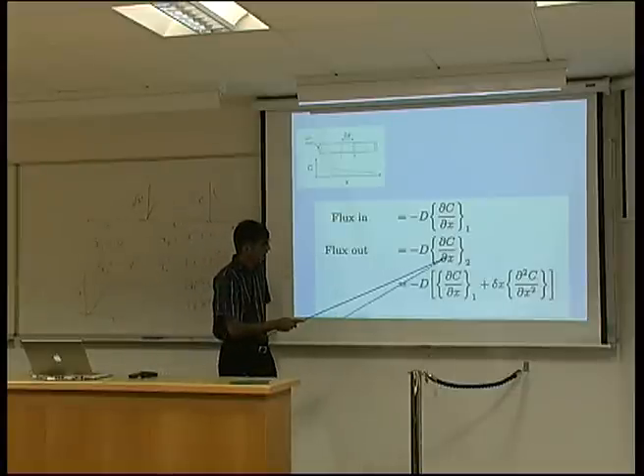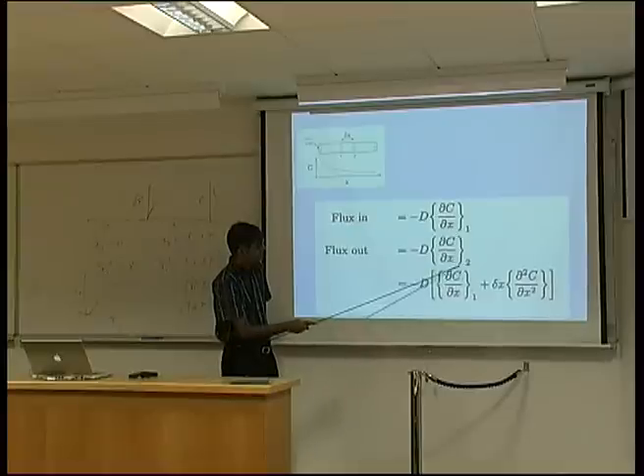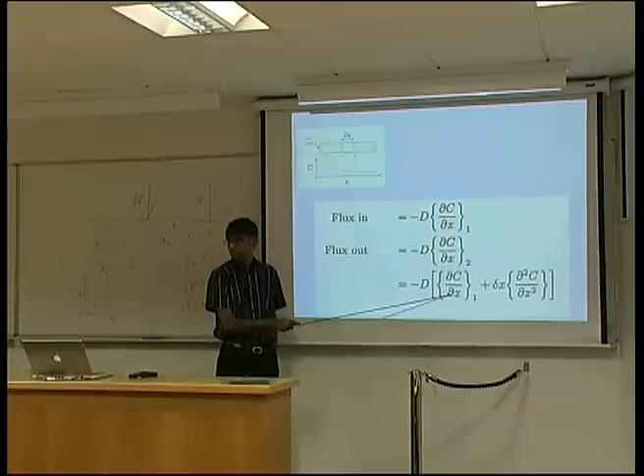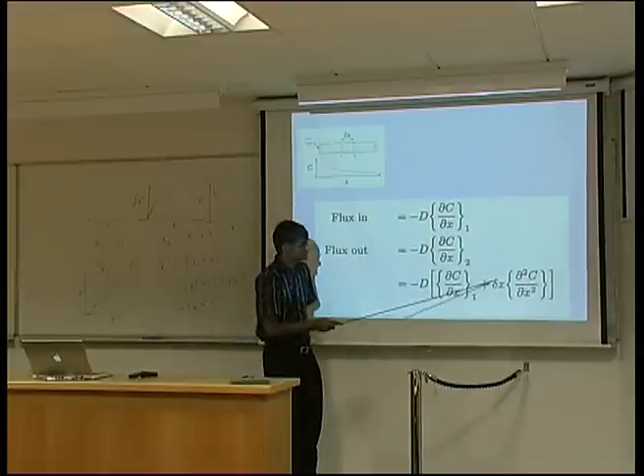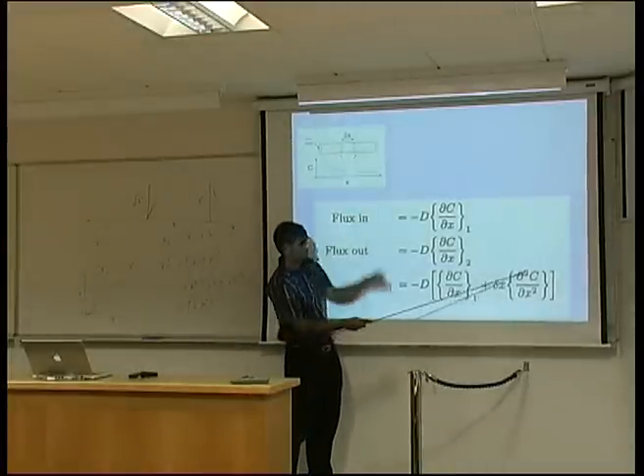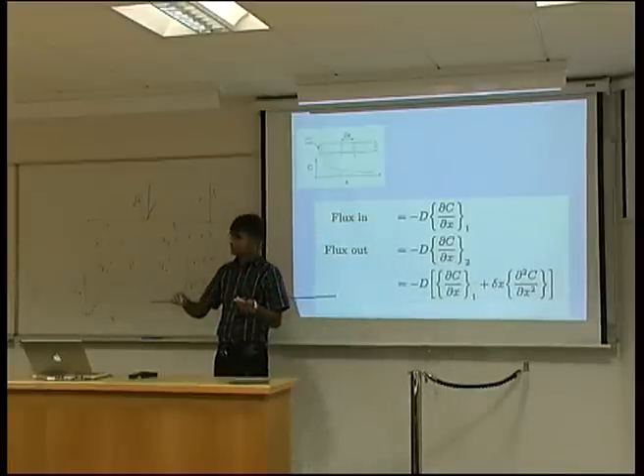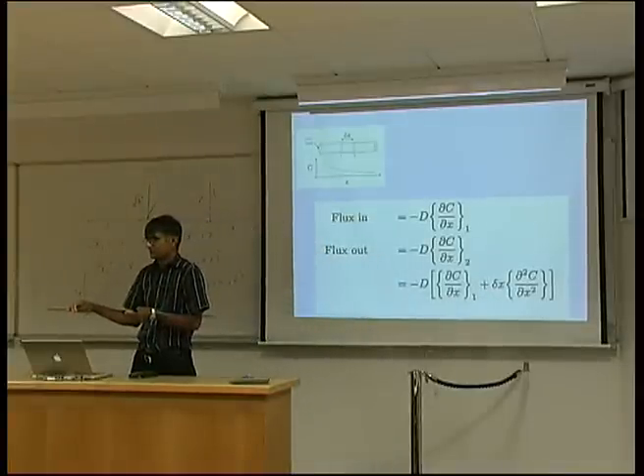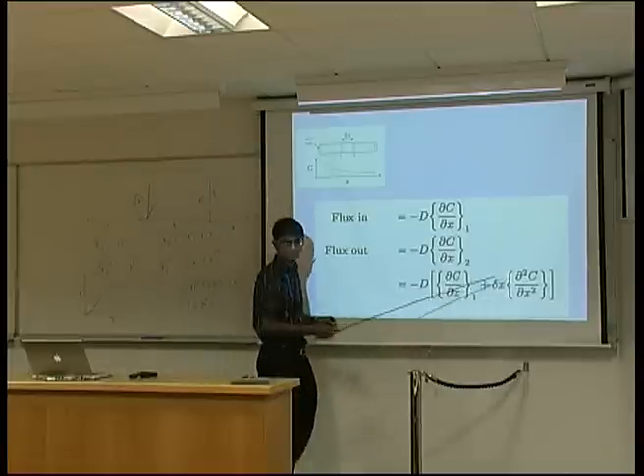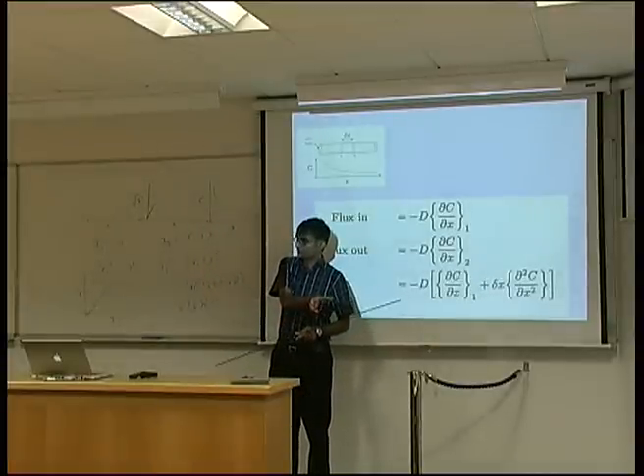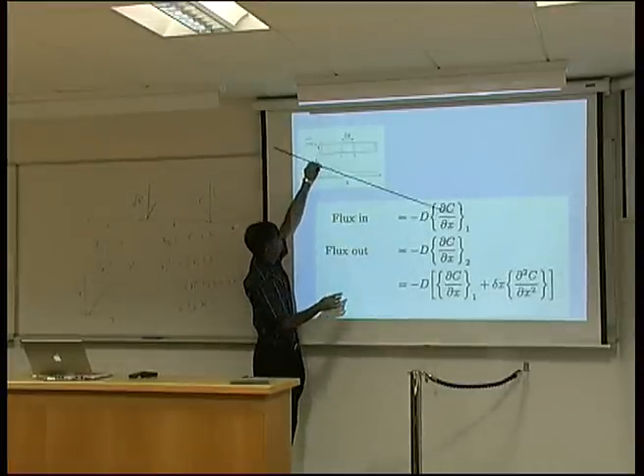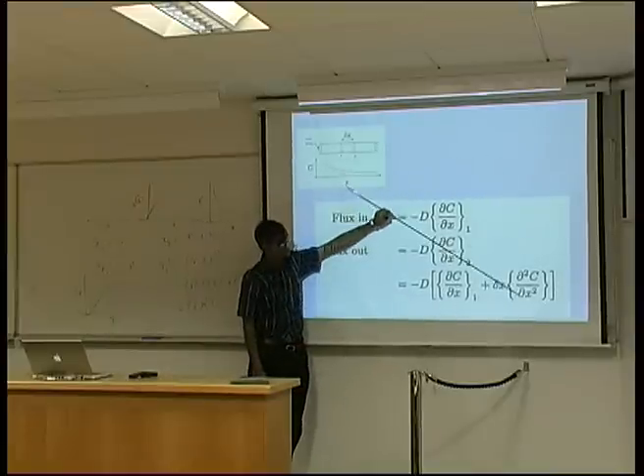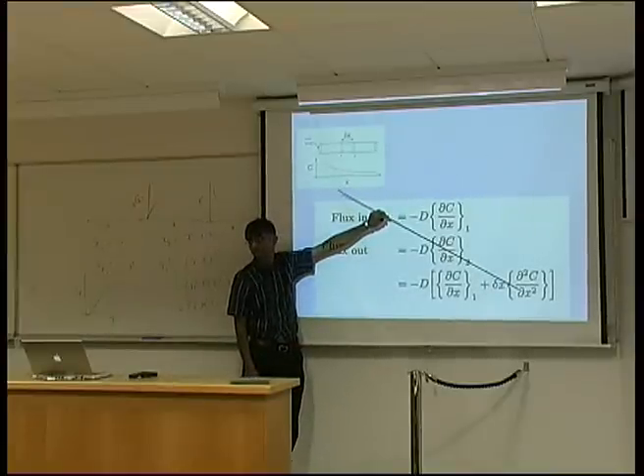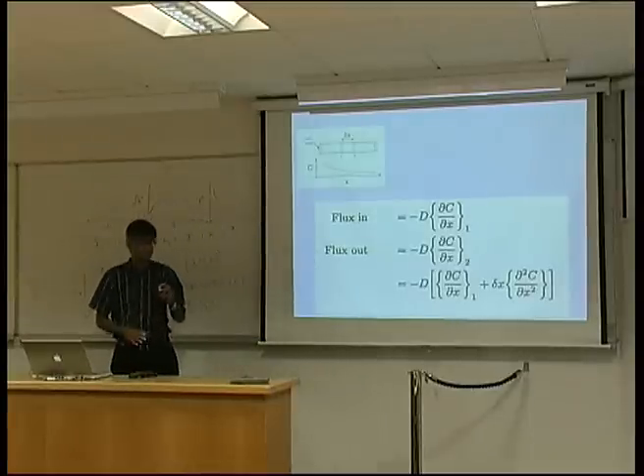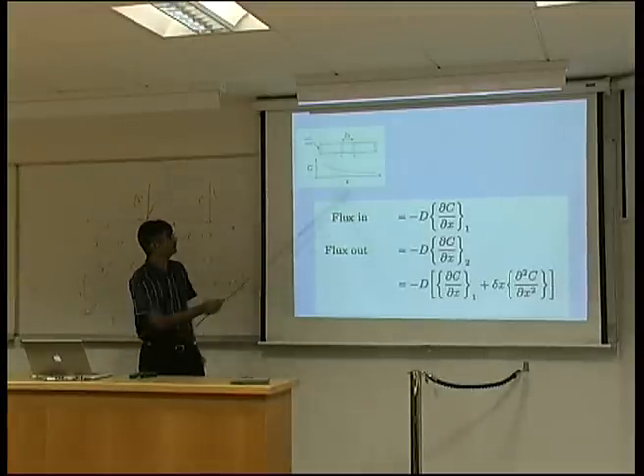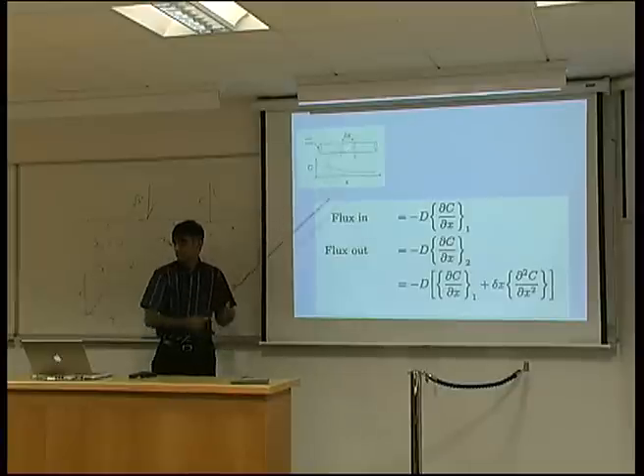Okay, so let's replace this by saying this is equal to the gradient at point 1 plus the distance delta x here times the rate at which the gradient changes with distance. d squared c by dx squared is simply how the gradient is changing with distance here. So you can see the slope over here is changing with distance. That's all that term is. Yeah? And then it becomes very easy because we take the difference between those two to find the change in concentration here as a function of time.